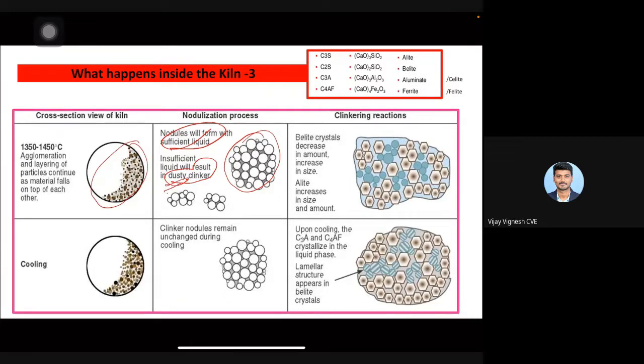This is another area of research. Then what else can we learn? Belite crystals decrease, like dicalcium silicate decreases in amount, but increases in size. In alite, it increases in size and amount. Quantity also increases, size also increases. In the kiln, we have the solid compound. After that, the calcination process, it becomes semi-liquid and changes the phases. After cooling to room temperature, the clinker nodules remain unchanged during the cooling.